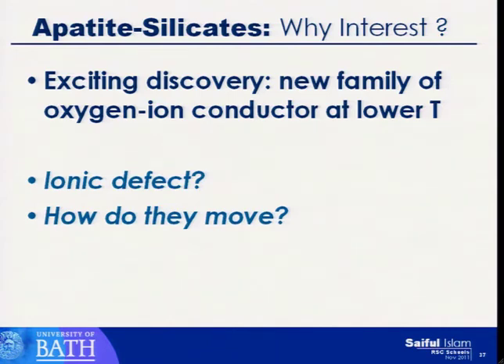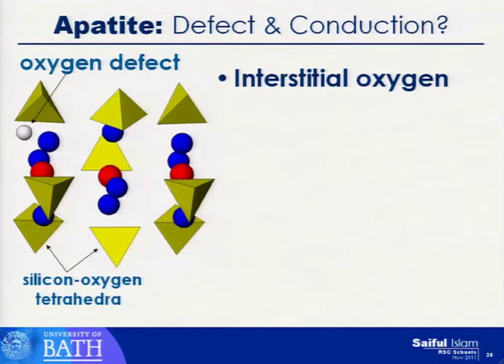They're new structures, so they're not well established. So we decided to do some modeling work with neutron diffraction. Neutron diffraction is a very powerful diffraction technique which allows you to look at isolated defects. And we made a discovery that was unexpected. The unexpected result was that the defect was oxygen, which wasn't unexpected, but the location was.